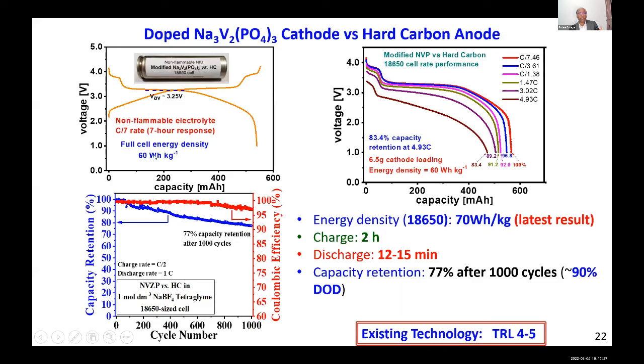That gives me an energy density of 60 watt-hour per kg. I must confess that this has been now improved to 67 to 68 watt-hour per kg with a certain further modification, but I'm not able to include those data at the moment. So we are somewhere about 68 to 70 watt-hour per kg. If you go for the soft packing, it is equivalent to about 90 watt-hour per kg.